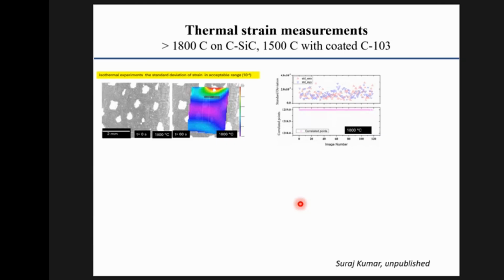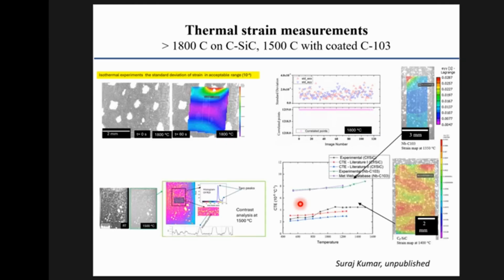So using this, we were able to carry out thermal expansion measurements. This is for niobium alloys. You'll have one set of curves from the literature and one from the DIC measurement. And this is carbon fiber silicon carbide. You'll notice there's a reasonably good correspondence between what we're measuring.